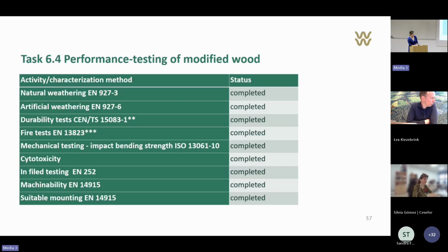The next step was performance validation. We had a screening phase, but then wanted further tests to identify the real performance, and whether the application we had in mind, mainly cladding for wooden facades, is feasible for this treatment. So we ran natural weathering, artificial weathering, durability tests, fire tests, mechanical testing, and cytotoxicity to prove the formulations are not toxic. We also had in-field testing for in-ground durability, and tested machinability and suitable mounting, because we wanted the materials to be workable and implemented in the demo building.